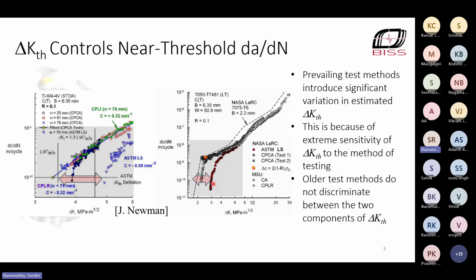But even my colleagues at ASTM, with whom we have discussed this quite a lot, say that the prevailing standard, ASTM E647 and its equivalents in ISO, don't focus on threshold. They focus on the intermediate range of crack growth rates, which are used quite a lot in engineering application, but for other purposes, not for determining safety or life between inspections or even total life. They're also used extensively in research simply because you can finish your experiments quickly when the crack grows fast. You don't want to spend weeks trying to get a result, particularly with our power shutdowns and things like that.